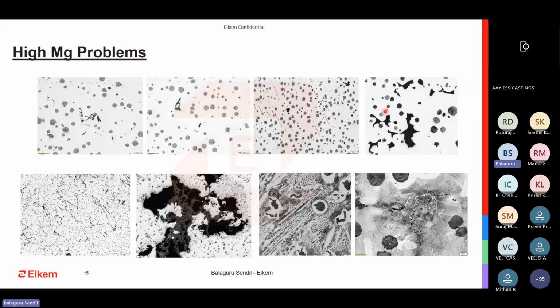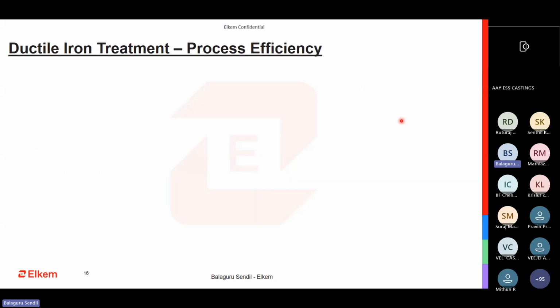But if it is quite big, then you need to go for compensating with a riser. Or you need to put a chill. Chill will not solve the problem of shrinkage. It will just move it to somewhere else. So one of the major reasons when it comes to nodularization and magnesium is that you must keep it as low as possible. Operate it with bare minimum levels. Achieve your residual magnesium using very low magnesium, so that whatever you are measuring is of useful micro inclusions rather than free magnesium. When you have that, then we can definitely work on having your yield optimized.